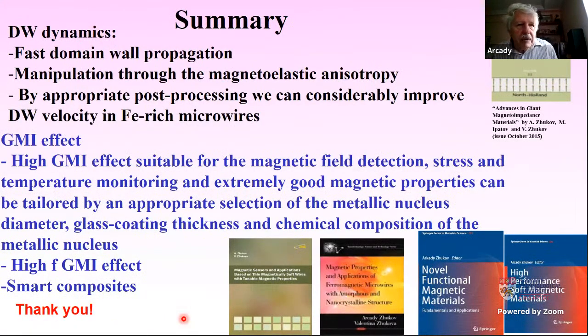And in summary, I want to say that magnetic microwires can present different exciting properties. For example, fast domain wall propagation, which could be manipulated through the magnetoelastic anisotropy, and the appropriate post-processing is quite important. And the high magnetic impedance effect is suitable for different applications like magnetic field detection, stress and temperature monitoring, and quite good properties could be obtained.